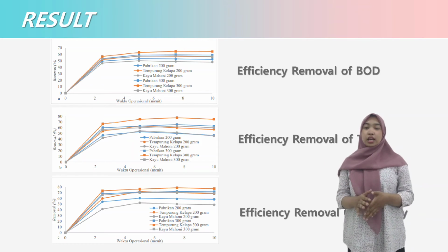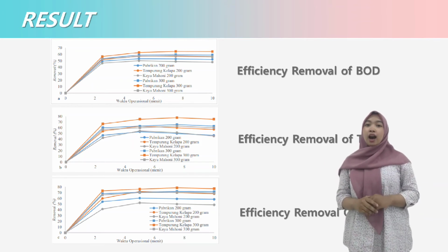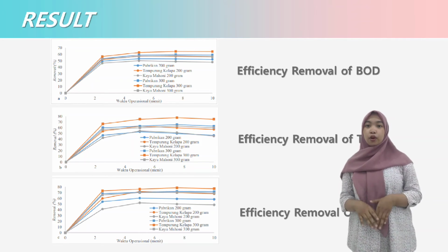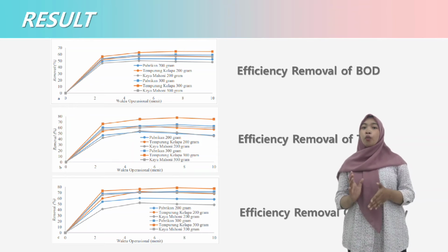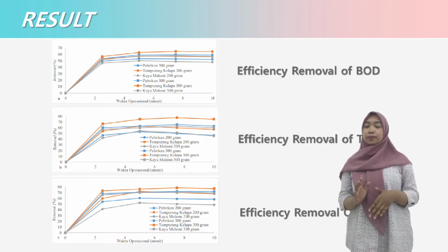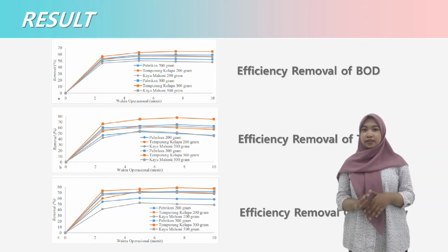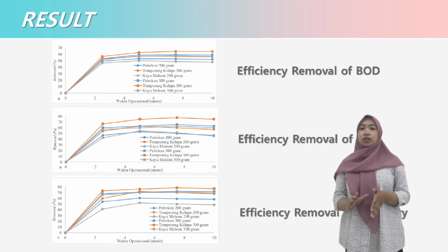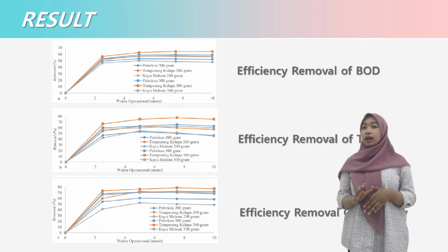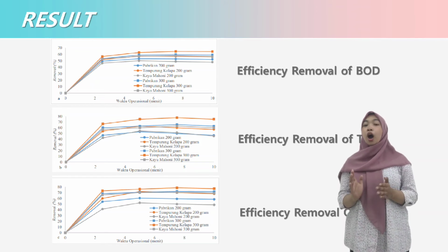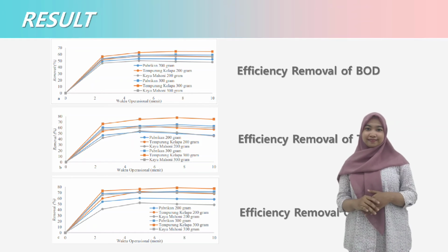The removal efficiencies were 64.6%, 77.8%, and 78.46% respectively. This is because the water content and ash content of coconut shell activated carbon are lower than the moisture content and ash content of Pabrikan activated carbon and Mahogany activated carbon.